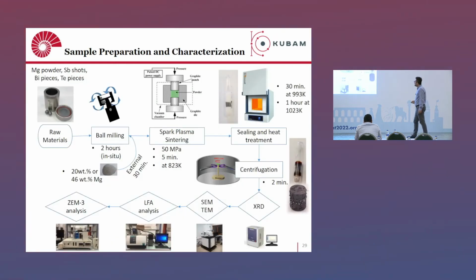Let me explain it to you here. So you can put all these materials in a steel vial and do high energy ball milling, let's say 2 hours of high energy ball milling. If you add the magnesium at the very beginning, this is in situ. After you do this 2 hours ball milling, if you add the external magnesium afterwards, this is called the ex situ preparation. So this will lead to powder material.